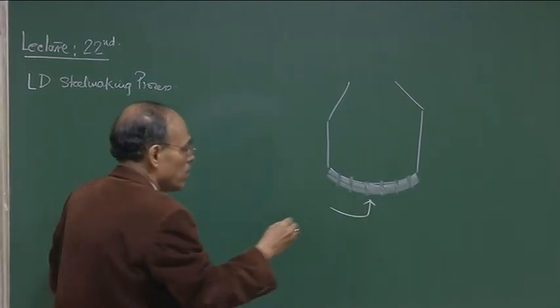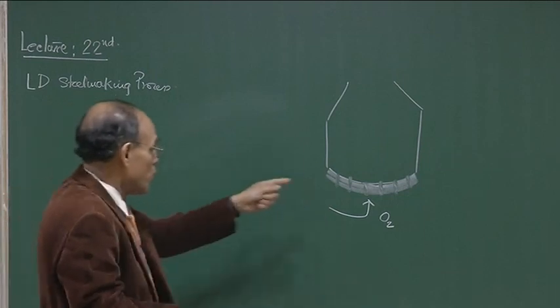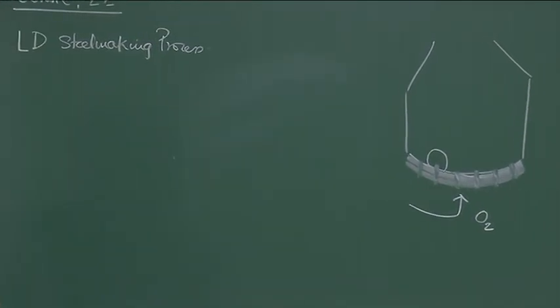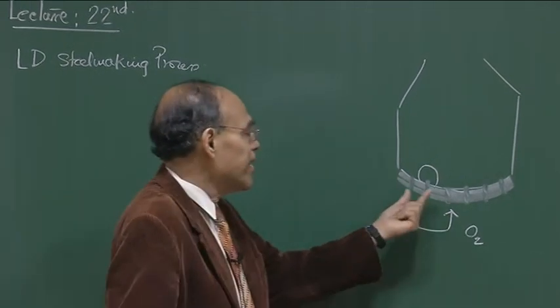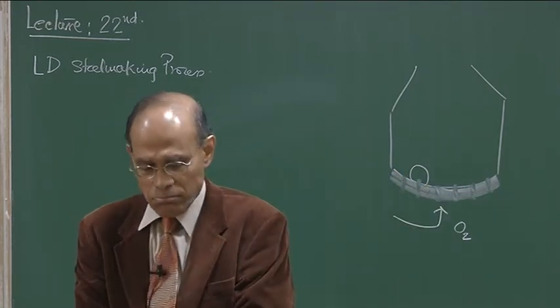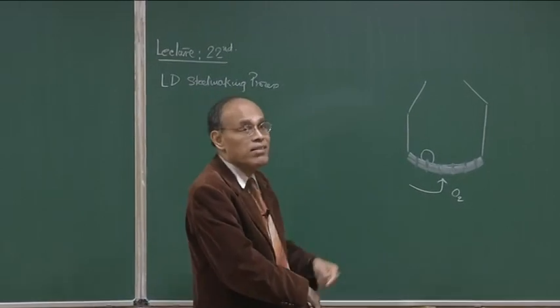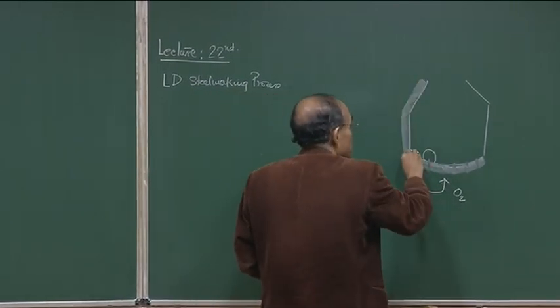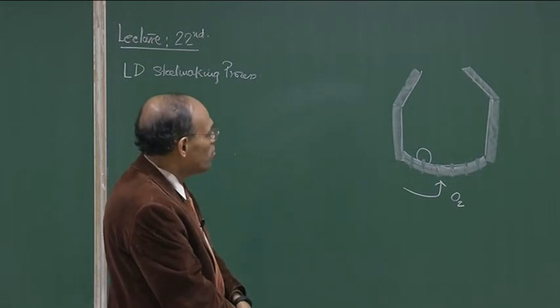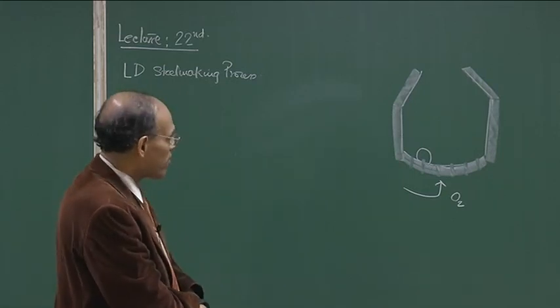and initially also, in the same Bessemer vessel through the tuyeres, when attempts were made to blow oxygen, disastrous consequences were met. The heat produced in the vicinity of the tuyeres because of metal oxidation reactions, which are known to be extremely exothermic, damaged the tuyere as well as the localized refractories in such a way that almost on a weekly basis the converter required relining, making it not a commercially viable process. So, attempts to blow oxygen from the bottom, from the side, also through a submerged lance, produced no results because of the intense heat that got generated and damaged the refractory.